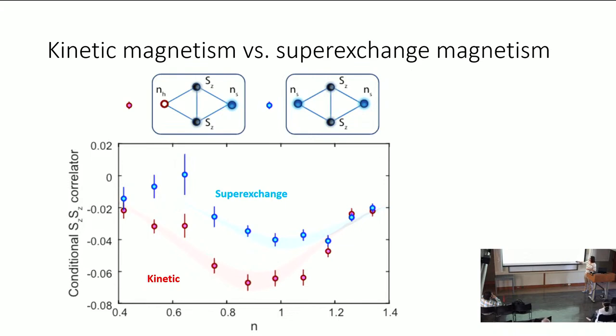And we see that, yes, indeed, this correlator is negative for a range of dopings, so there is superexchange still, as expected. However, when we condition on one of these sites being a hole, not only is superexchange allowed, but this kinetic frustration is also allowed. And that, we see unambiguously, leads to a stronger type of antiferromagnetism. So this, for us, was a strong indicator that what we see is qualitatively different than superexchange.